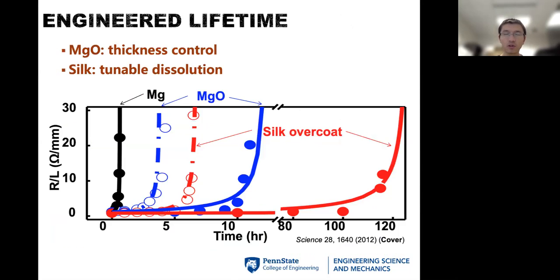And of course, if you make every single material biodegradable, the device may not even be functional. That's why we want to make sure the device can stably function for a certain period of time, say a week, a year, or whatever you have in mind, and then safely dissolve. Here, if we look at magnesium, it doesn't dissolve slowly, but rather within half an hour. But if we encapsulate this 300 nanometer magnesium with 400 nanometer magnesium oxide, you can extend the lifetime to about 3 hours. If you double the thickness to about 800 nanometers, it can increase the lifetime to about 10 hours.